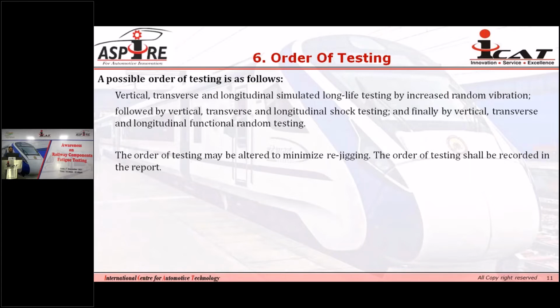For example, if testing of railway components is being carried on the vibration shaker, and if we carry the functional test as per this order, vertical, transverse, and longitudinal, in that case we have to do multiple rejigging. So to avoid the rejigging, there is an option to alter the testing order to avoid the rejigging of the test setup.